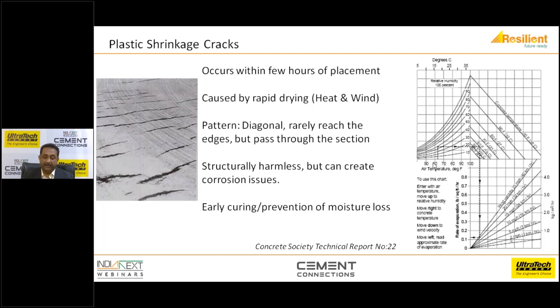It's a combination of air temperature, which you can see over here, and this is the relative humidity. So lesser the relative humidity, more is your evaporation loss. So suppose you take, this is in Fahrenheit, so you need to convert into centigrade if you're comfortable with the centigrade, which we are all. And from this, you find out what is the placing temperature of concrete.